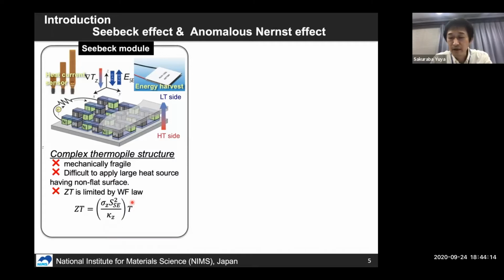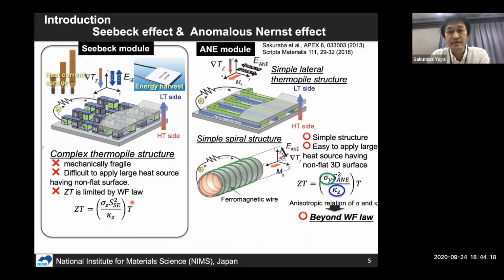However, when we apply the anomalous Nernst effect to thermoelectric applications, we don't need to make this kind of complex thermopile structure anymore. We can easily increase the serial voltage by making a laterally connected ferromagnetic wire like this. Because the electric field of the anomalous Nernst effect appears along the surface of the heat source. So in this figure, the magnetization direction is the X direction, so the electric field of the anomalous Nernst effect appears in this direction, the Y direction. So we can easily obtain a high serial voltage by making this kind of simple laterally connected structure. Because of this simple structure, it is easy to apply to a large heat source having a non-flat surface.